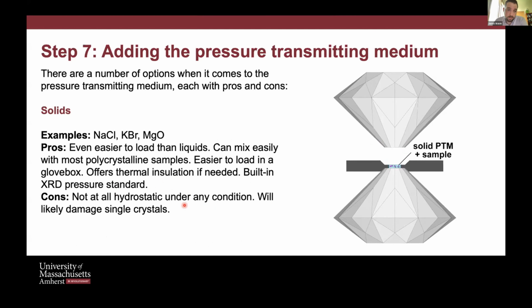The other option is solids. Again, Stas mentioned this. Sodium chloride is a common solid. I've talked about using MgO as a pressure medium. It's even easier to load than liquids because you're not having to do it quickly before the thing evaporates. And you can mix it if you're doing polycrystalline samples or flakes like we use often. That's relatively easy to load. And it can also offer thermal insulation if you need that, if you're doing laser heating. And it's also a built-in pressure standard, so sometimes you don't even need ruby.